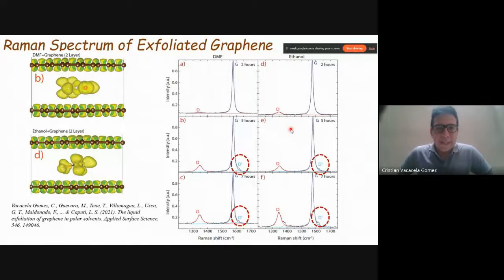Now, let's analyze the Raman spectrum of exfoliated graphene. Before analyzing the Raman spectrum in this work, we also completed the characterization using density functional theory computations. If you remember the different processes, the idea of exfoliation is to increase the van der Waals interaction distance between the graphene layers to obtain graphene layers. From the sonication part, how can we do that? Of course, the mechanical waves increase the distance between graphene layers in the graphite structure and introduce solvent molecules. That is the idea of this representation.